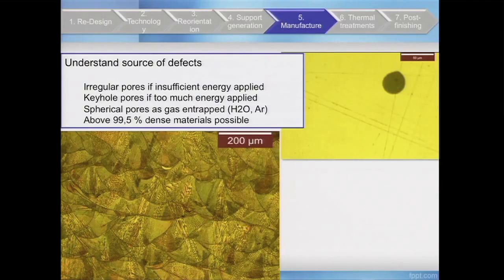Indeed, you may find, sometimes if you don't have the right settings, defects. For example, there are 3 types of defects that you may encounter, speaking in general. You can have irregular pores. That means that you are not applying enough laser power. You can have spherical pores that can come from moisture in the powder or from the argon that you use during the process. And you can have keyhole pores that appear when you really apply too much energy.